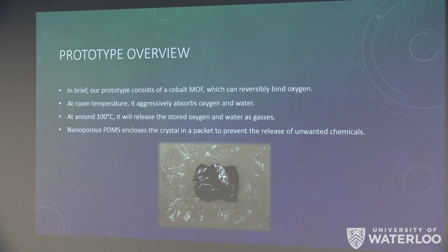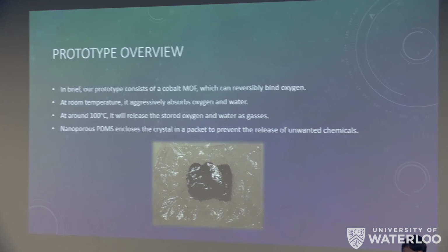So our prototype is a cobalt-based metal organic framework. At room temperature, it aggressively absorbs both oxygen gas and water vapor. It absorbs oxygen down to under 1% when available in sufficient quantities. It's very aggressive at absorbing water vapor. For example, when left overnight in our glove box, it pulled water from the atmosphere so strongly that about half a pound of Drierite, a specific compound intended to be disposable to dry vapor from the air, actually had the water sucked out of it into our product and returned to its original state. This was a much larger reaction than we expected.